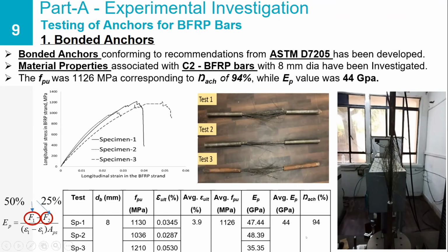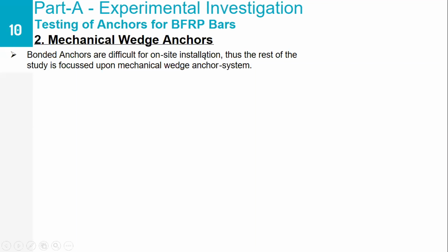So the anchor efficiency, which is basically the strength that we got by testing these bars using the bonded anchors, was around 94%. However, these bonded anchors are difficult for on-site installation because the fabrication procedure for these bonded anchors is quite complex and involved, and we do not have so much time and facilities at site to construct all these bonded anchors in large numbers. So hence the study has been further conducted on the commercially available mechanical wedge anchors for the rest of this project.